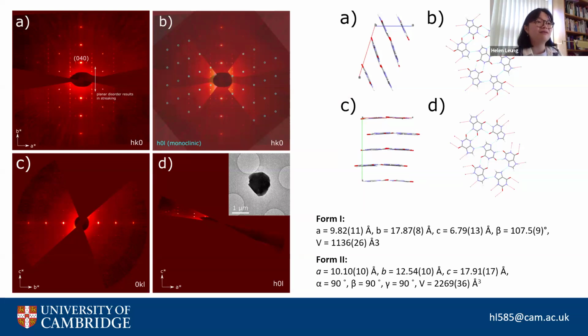And the way that they're related is, if you look at panels B and D on the top right corner of this slide, you can see that the layers are essentially the same. So the xanthine molecule arrangements within those hydrogen bonded layers are essentially unchanged, their coordination. And so this makes this a very specific type of polymorphism, which we call polytypism. So these are polytypes of each other, and that's just a subset of polymorphs. And you can see where the extra reflections come in blue. I've highlighted in the sections here in panel B where the extra reflections are introduced when you have orthorhombic symmetry.